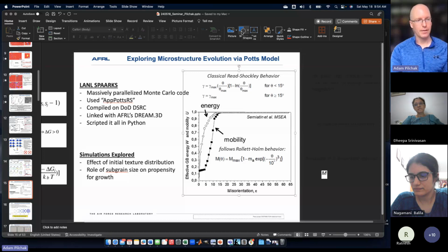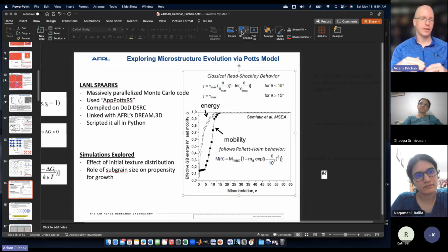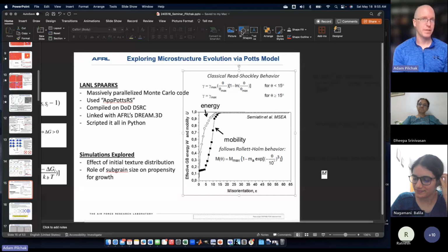We actually tried to do that. Lee Semiatin started doing that probably while I was still an undergrad. He created a sheet with really large beta grains and then cut it, trying to ensure that the grain boundaries were perpendicular to the surface. It was a 12-inch by 12-inch sample. EBSD was done on the entire thing, both sides. The grain boundary curvatures, dihedral angles, everything was measured. This was over the course of like 20 years by multiple different students and postdocs, myself included. And I provided the last piece of the puzzle, which was the grain boundary curvatures.